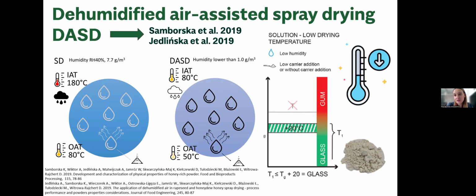In traditional spray drying, the drying air humidity is around 7, 8, 10 grams per cubic meter, obviously depending on the external conditions. And the standard spray drying temperature is around 180 Celsius degrees at the inlet and around 80 Celsius degrees at the outlet. And due to air dehumidification, when the drying air humidity is lower than 1 gram per cubic meter, the inlet air temperature can be lowered to 80 Celsius degrees and the outlet to 50 Celsius degrees. So you can see that the temperature drop is quite significant.